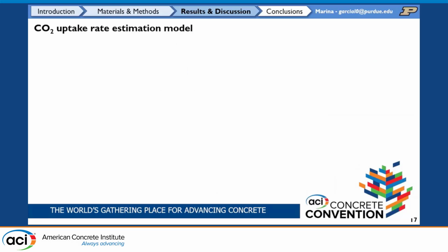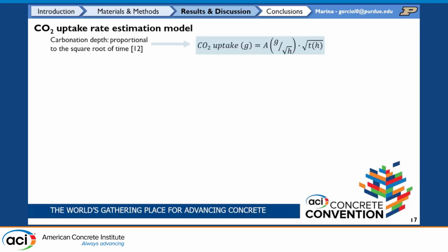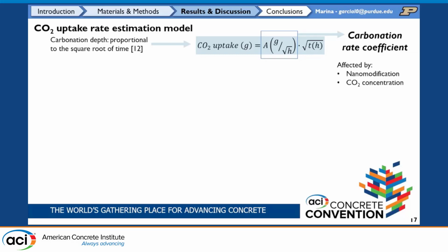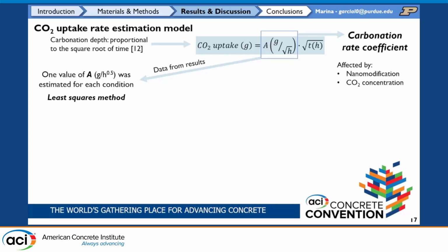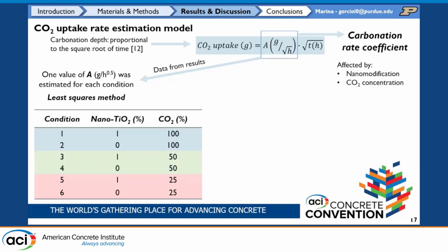And with all of this data, we decided to come up with a CO2 uptake rate estimation model. We know from the literature that carbonation depth is usually proportional to the square root of time. So what we came up with is this equation: the CO2 uptake in grams is equal to the carbonation rate coefficient, which is something that we came up with, times the square root of time. And this carbonation rate coefficient is affected by both the nanomodification and the CO2 concentration that we have. So with this data, we estimated the carbonation rate coefficient for each of the conditions using the least squares method. And these conditions were the two percentages of titanium dioxide nanoparticles and the three initial CO2 concentrations.